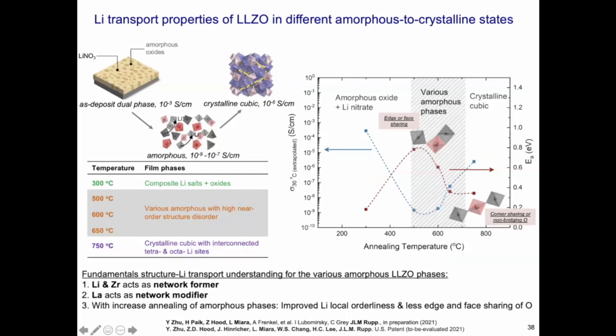And I want to highlight work from the Weizmann, from David Ehre and Igor Lubomirsky, where they showed that in amorphous perovskite such phenomena exist. However, we have four local bonding block units compared to a perovskite that would technically only have one. So it's far more complicated. What we can say right now is that the lithium and the zirconium, and there's EXAFS and NMR evidence, act as a network former with their building block units, whereas the lanthanum acts like in a classic glass as a network modifier. And we can see that with increasing annealing of the amorphous phase, we see improved lithium local orderliness. However, it has a peak. And it depends on how much edge and face sharing you have of the local bonding block units for the oxygen to bridge, and how the lithium is later diffusing through.